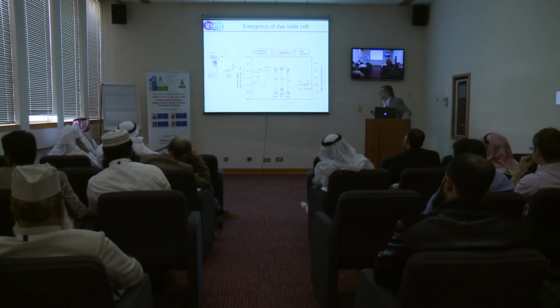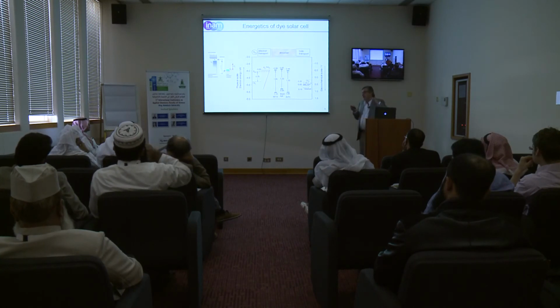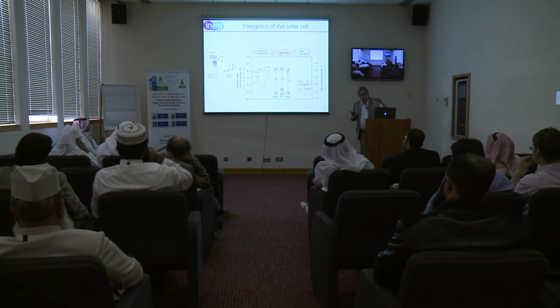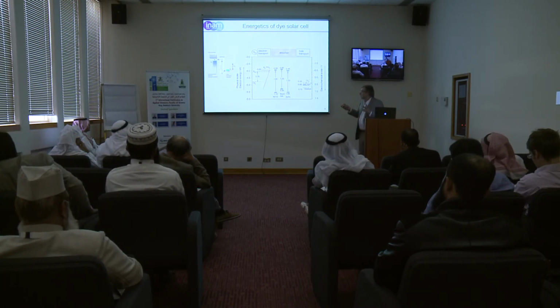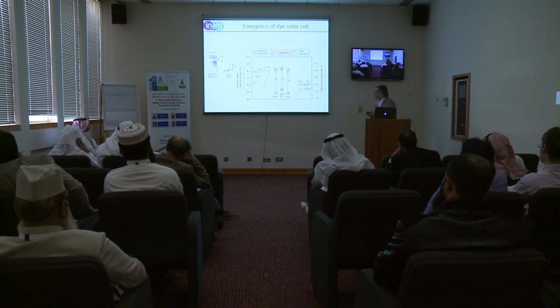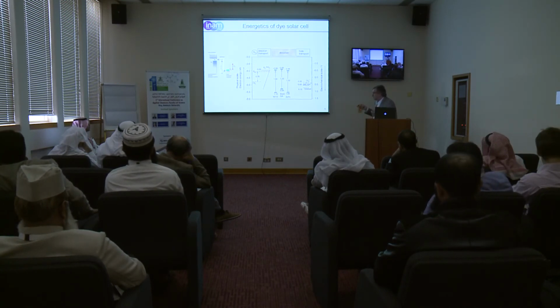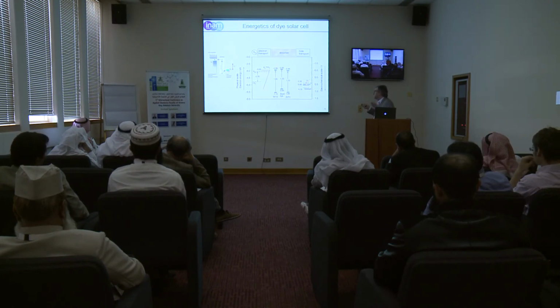So based on the recognition that we can identify the chemical capacitance with the density of states with respect to a reference energy level, which is the redox potential in the electrolyte, we can make this total map. This is a total map of energetics. This is the drawing I showed at the beginning, which was approximate. But now here it is totally quantitative, and you see something here commented already by Anders Hagfeldt and other people.